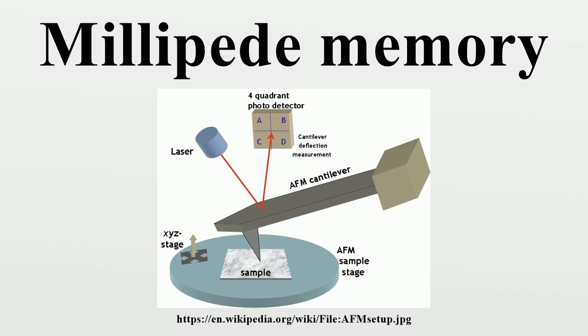The design of the cantilever array involves making numerous mechanical cantilevers on which a probe has to be mounted. All the cantilevers are made entirely out of silicon, using surface micromachining at the wafer surface. Non-cross-linked polymers retain a low glass temperature, around 120 degrees Celsius for PMMA, and if the tip is heated to above the glass temperature, it leaves a small indentation.